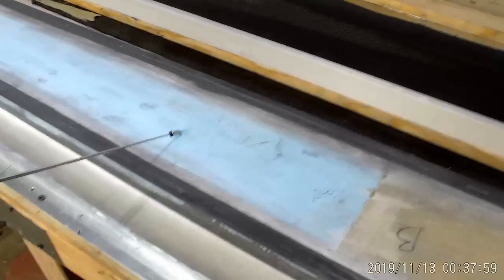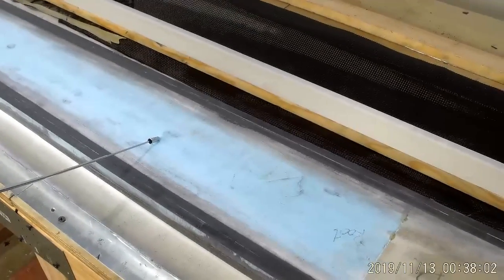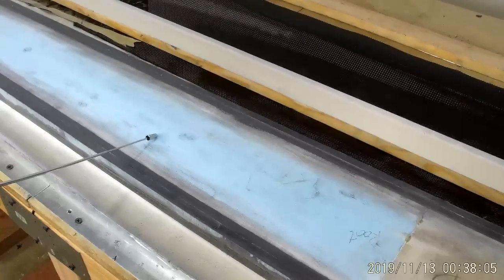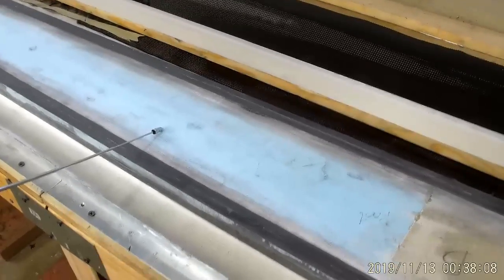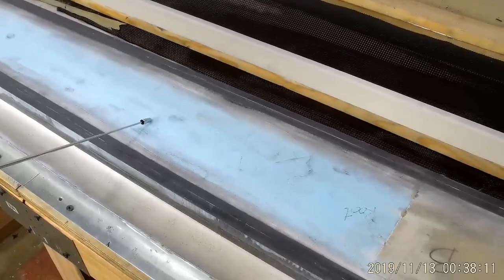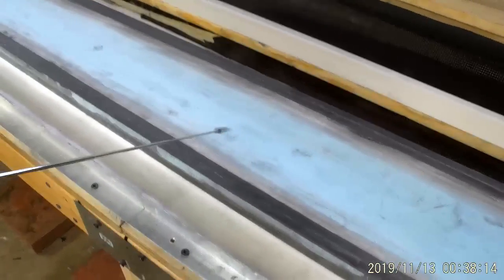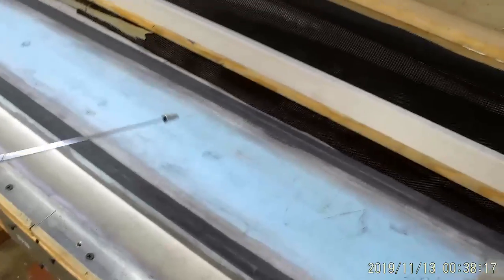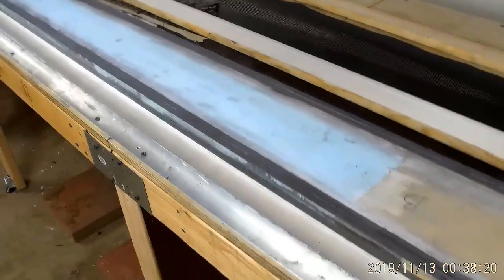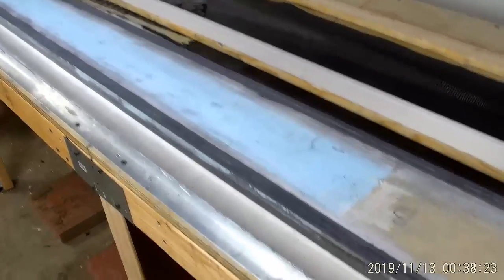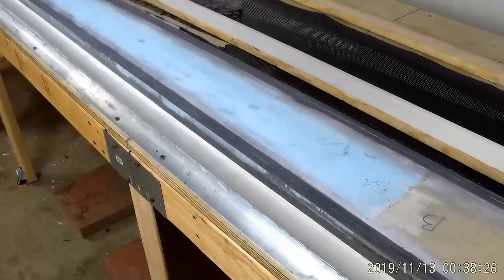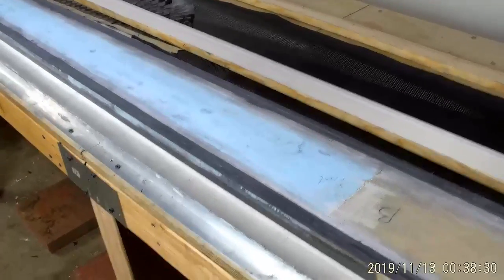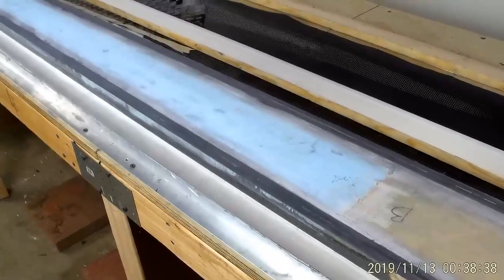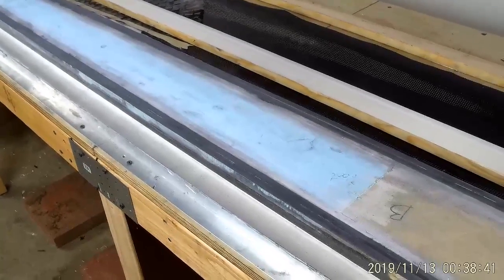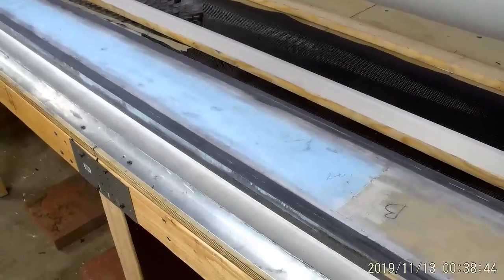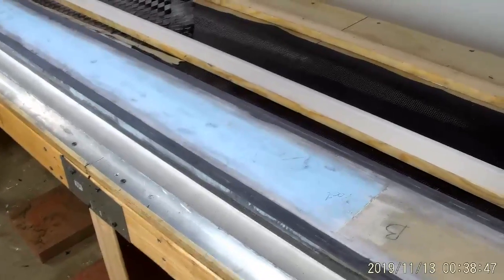I forgot to mention earlier, one of the key things I like about the extruded polystyrene foam, it might have some other drawbacks, but its big plus is extremely tight cell structure, and the cells are closed. So very little epoxy actually goes into the foam when you do the layup. You may note on most of my layups, I wet out the fabric prior to applying it to the foam, and that is because of that open cell structure on the foam. I'm using the excess resin that's in the fabric to bond to the foam. If you were to put the fabric on the foam first and then wet it out, all of those cells fill up with resin.